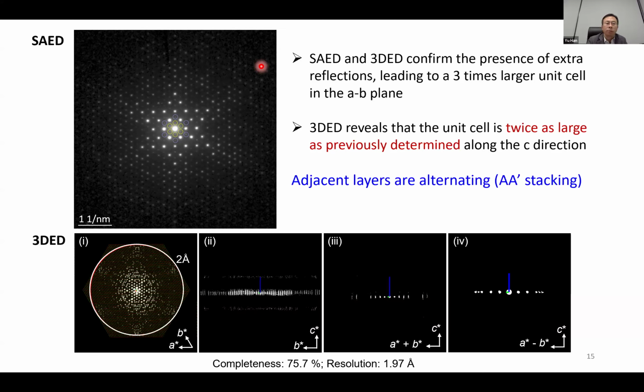Okay. We didn't do a systematic comparison, but I think it's comparable because for MOF materials, even in the electron diffraction pattern, the highest spatial frequency is around 1 angstrom or something like that. It's difficult to get sub-angstrom resolution even with diffraction. But I will double check that and I will let you know.